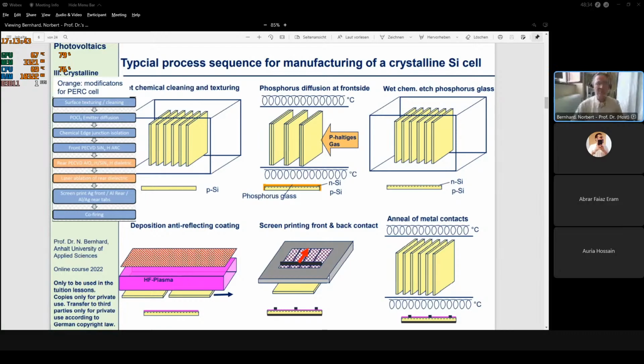And what is done is that saw damage is removed, saw damage removal, because before that, of course, all these wafers are sawed from an ingot, and then of course the surface still has the saw damage, because sawing is a rather coarse process. And at the same time, we do something which is called texturing. That means it's a micro roughening of the surface. I will explain in a minute what the purpose of this is.